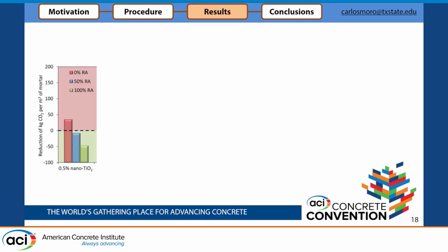Okay? We can see that with a small percentage of nano titanium dioxide, the CO2 emissions are improved. That means that we have lower emissions with higher amounts of recycled concrete aggregate. That means that the recycled concrete aggregate is playing a role here. Why is that? Because the recycled concrete aggregate has a higher porosity. That means that the nanoparticles can improve even further the densification of the microstructure. So in that case, it can improve even further the compressive strength and then reduce the cement content needed to achieve a similar performance.